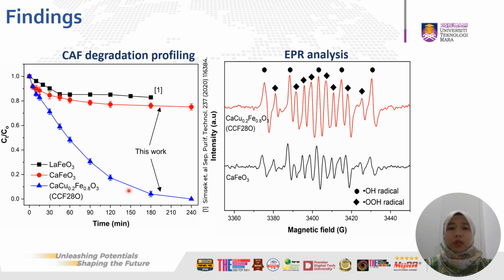CCF28O perovskite catalyst, shows a complete caffeine degradation was achieved within 4 hours of reaction. The result of this work basically has surpassed the findings obtained from the literature by Simsek in 2020 using the lanthanum iron oxide perovskite catalyst with only 11% of caffeine degradation. Such observation reveals that copper substitution into the calcium iron oxide activated hydrogen peroxide to accelerate the generation of the radicals, resulting in a much higher rate of caffeine removal.